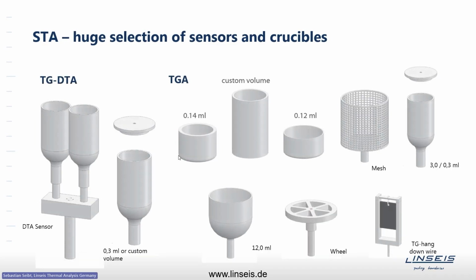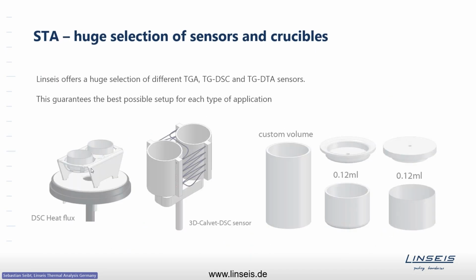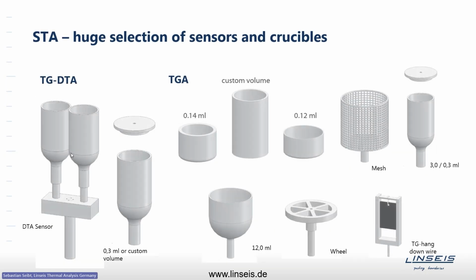Of course, you can also run the TG-DSC instrument as a TG only or as a DSC only. If you want to run it as a DSC, of course, you need a DSC sensor. However, if you want to run it as a TGA, you can exchange the sensor head and use a TG only sensor. We have TG-DTA sensors as well, which cannot quantify the heat flow, as you measure the heat flow just in one point and not with this sensor head out of metal where you measure the complete heat flow environment of a crucible. In contrast, the DTA sensor here has only 2 spot thermocouples that measure the temperature at each crucible at one point, allowing you to measure at least whether something is exothermic or endothermic and at what temperature something happens.